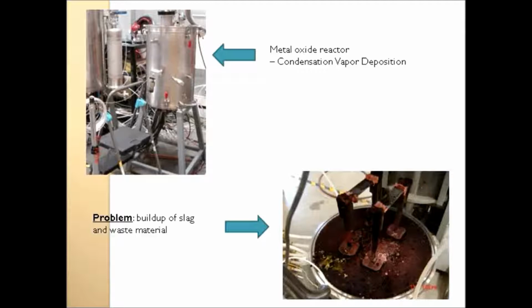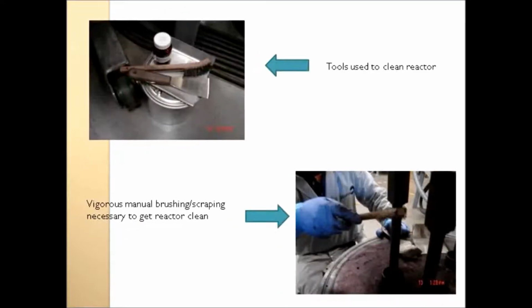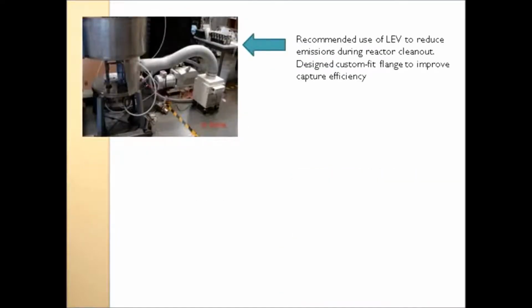So this is basically a low-cost, low-tech application for a high-tech operation. These materials are very fluffy, so we felt that if we could fabricate a flange that would encircle this reactor, as the worker is cleaning, it would corral, if you will, the material and draw it through the tube. It's running at about 1,000 CFM, cubic feet per minute, through a HEPA filter, and we looked at the exhaust of that unit and we got nothing. So it was being trapped by the HEPA filter.